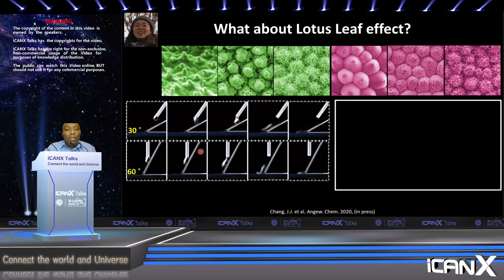And when we do that, of course we get these very rough surfaces. The videos are not playing here, but what I was showing here is actually these images in a movie where you put the droplet and it just rolls off. It doesn't stick at all. You cannot have the drops stay on the surface of these structures at all, because we have increased levels of roughness and we have more air trapped in there.